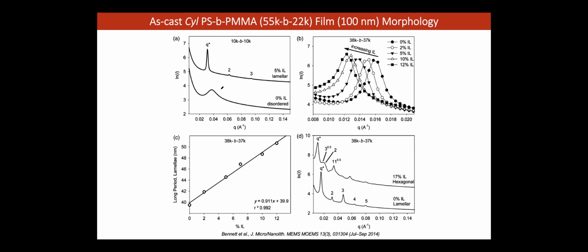It falls below 10.5, so it's disordered without ionic liquid. But you add ionic liquid and amazingly, it becomes highly ordered. This is now a GISAXS picture, horizontal cut, and it shows you a nice Q star value with second and third order a little bit, with just 5%